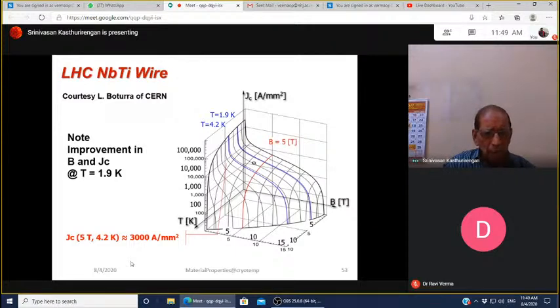I'll just show you one example here: the Large Hadron Collider, LHC, niobium titanium wire, courtesy of L. Botura of CERN. You can see here a three-dimensional figure in which you have temperature T on one axis and the magnetic field on the other axis. On the vertical axis you have the critical current, and you see a shape below which superconductivity exists. When the material crosses outside this curve, it is no longer superconducting. The JC, the critical current at 5 Tesla at 4.2 Kelvin, is approximately 3000 amperes per square millimeter. The units are amperes per square millimeter.